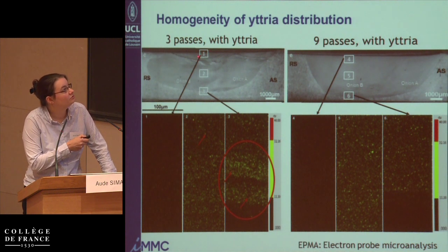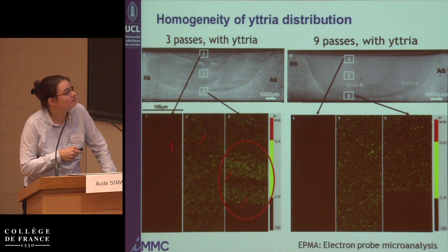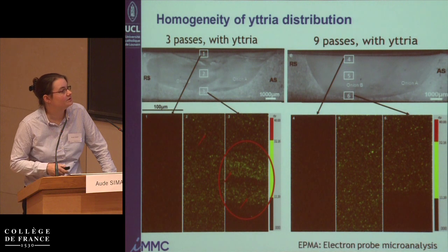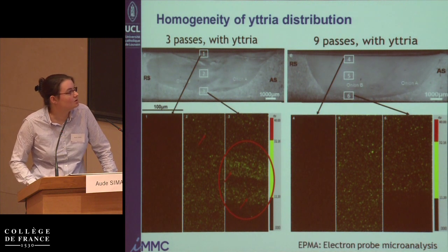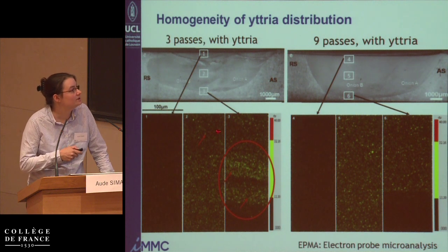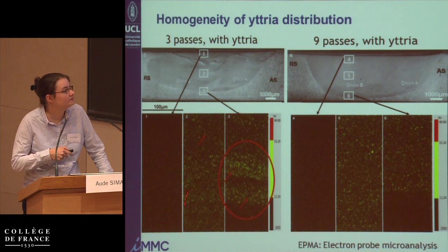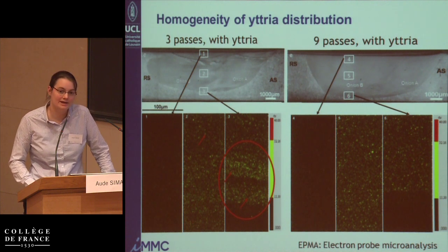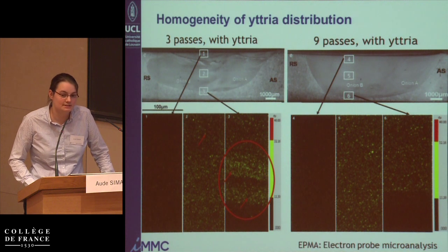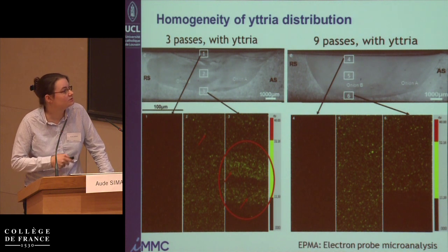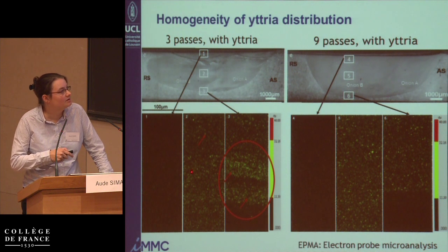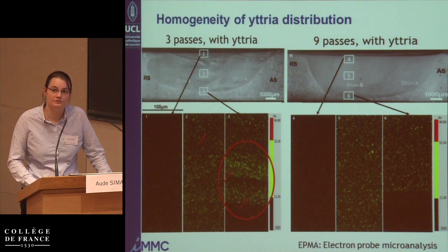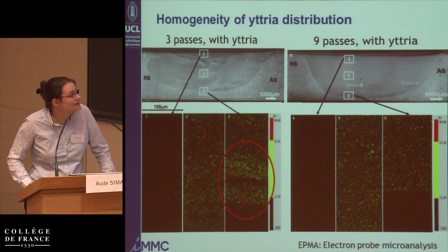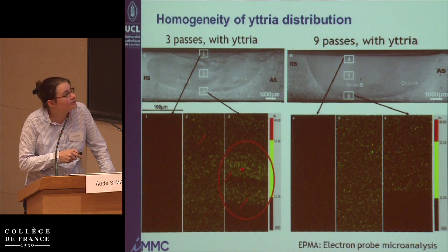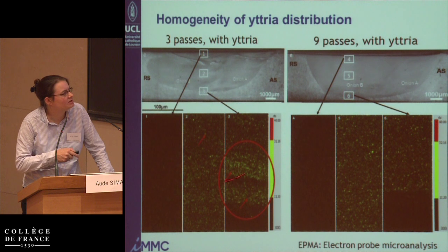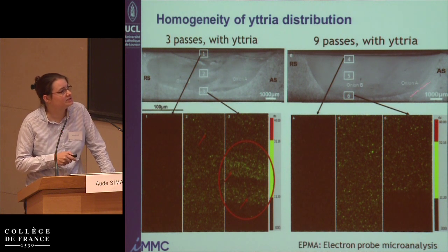So looking from top to bottom, you see that here on the top the quantity of oxide particles is rather low, and when you get to the bottom you have some clustering that you can see here. I must mention that this is electron probe microanalysis to identify the region. So in green here you have the higher proportion of yttrium oxide, and you see that here at the bottom of the nugget you still have some regions where the homogeneity is not too good, and the homogeneity is improved.